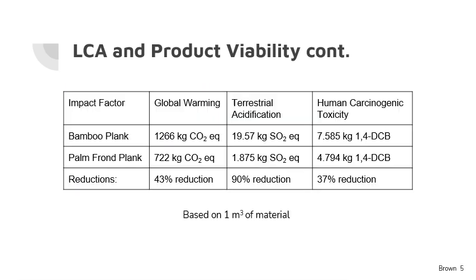And following this, the team conducted a life cycle analysis utilizing OpenLCA, using 1 cubic meter of material. And from there, we noted that the palm frond material had a 43% reduction in global warming, a 90% reduction in terrestrial acidification, and a 37% reduction in human carcinogenic toxicity. Following this research, we found that the palm fronds were indeed a more sustainable material.